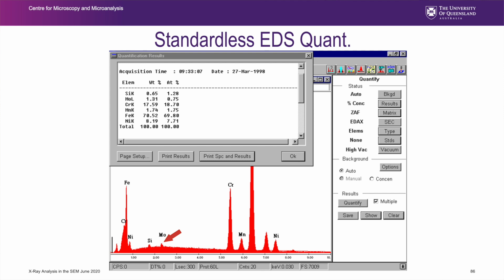Let's have a look at this. Look at how small that moly peak is. You can see it, but let's talk in terms of weight percent. That translates to 1.3% moly. And that silicon peak, you can see there, is about 0.6 weight percent. So you can see, as these concentrations get smaller and smaller, those peaks are going to be harder and harder to see.